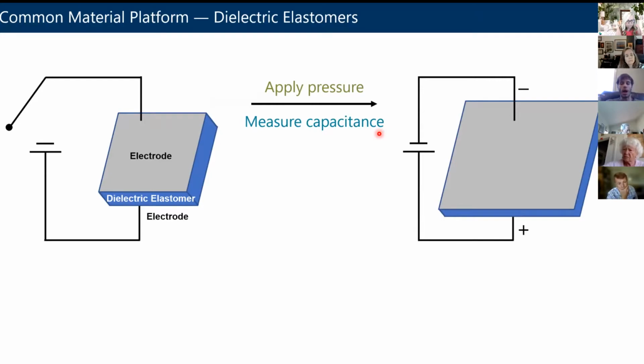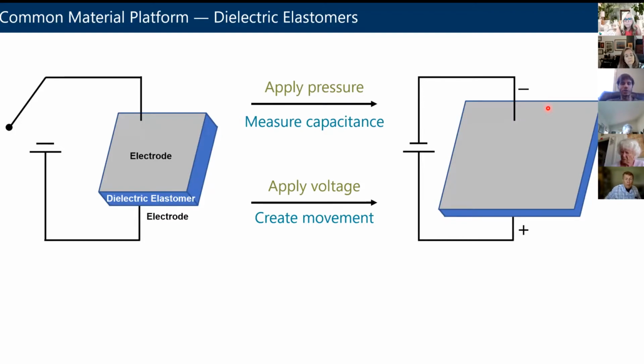Or you could operate this device in reverse, and you could apply a voltage across the electrodes, and that polarizes the layer in blue, the dielectric. And if it's a polymer, you'll create plus and minus induced charge, and those will attract each other and cause the device to physically deform because you're squishing that elastomer layer using a voltage. And that's a type of actuator. So you can turn pressure into an electrical signal, which is a pressure sensor, or you can turn an electrical signal or voltage into movement, which is an actuator, with the same kind of device.